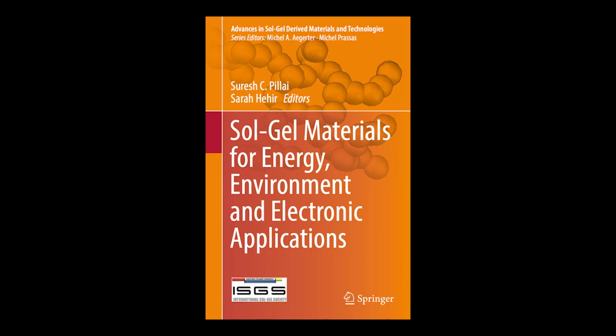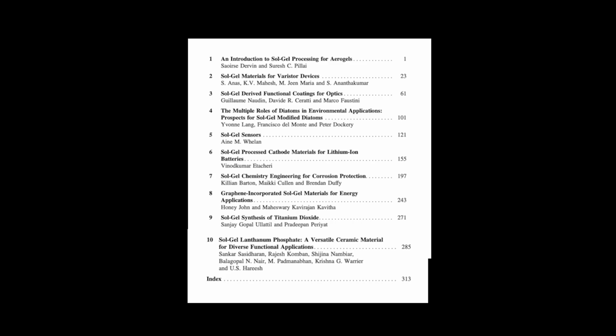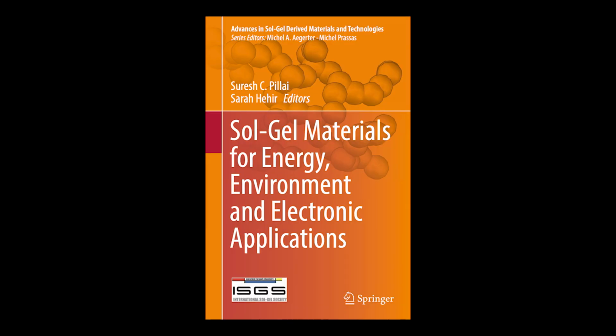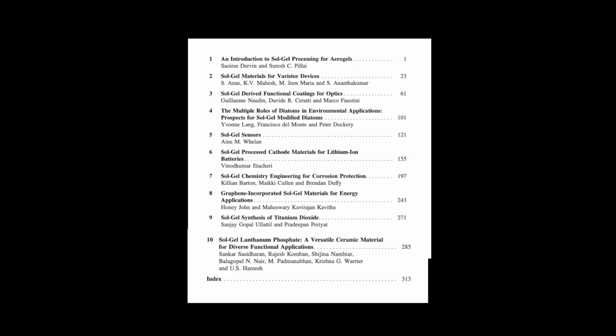Okay. We briefly touched on adding organic inhibitors like benzotriazole, BTAH, into these coatings. Are they comparable in performance to the cerium-based self-healing systems? Generally, the chapter suggests no, not for the active healing part. Organic inhibitors like BTAH definitely do enhance the passive barrier properties of the coating, making it more resistant initially. However, they typically lack the crucial mobility and responsiveness that characterizes the cerium salt systems. The cerium system dynamically reacts to the localized electrochemical environment, specifically the pH change. The organic inhibitors are generally static. They contribute to the overall barrier strength, but they don't possess that active, autonomous seeking and sealing mechanism that defines true, triggered self-healing protection in response to damage.